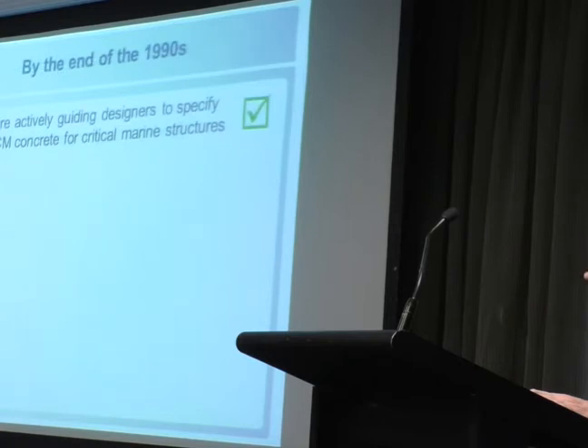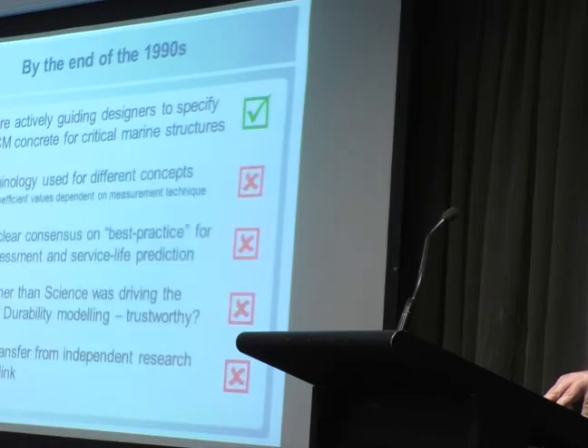So by the end of the 1990s, the models were routinely being used, and that was good because it was driving people to specify blended cement concretes rather than the Portland cement concretes allowed by the standard. And I think history has proven that the structures at that time that used SCM concretes are performing well, whereas the structures in more aggressive environments with Portland cement concrete are beginning to fail now, 20, 25 years later. But there are a whole lot of other black marks as well.